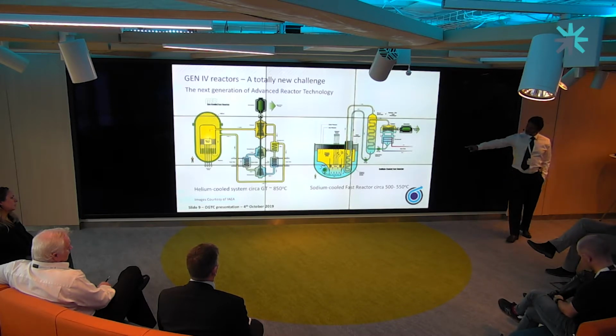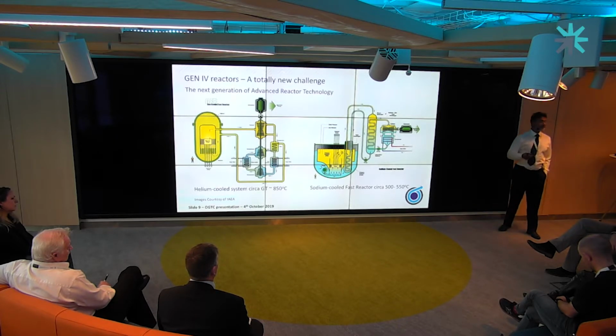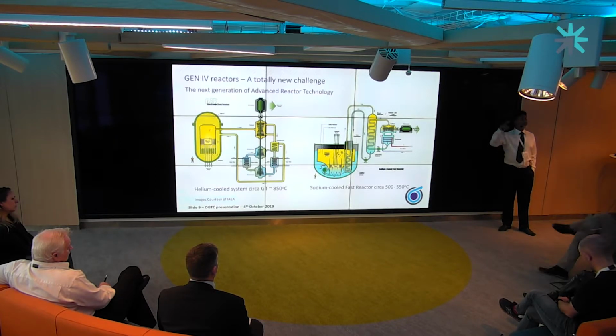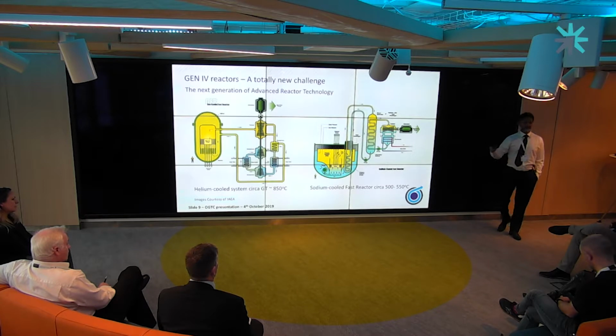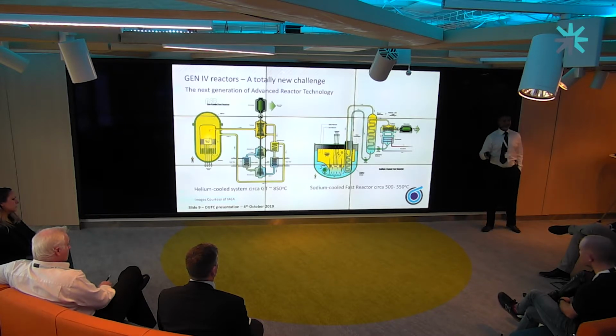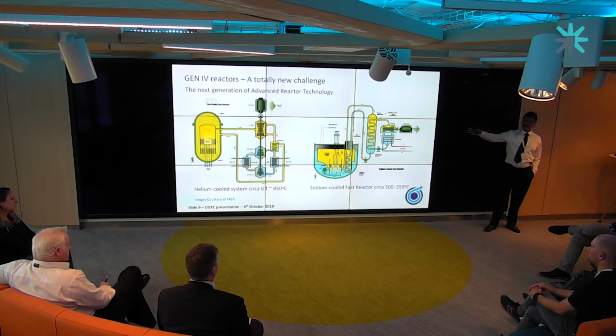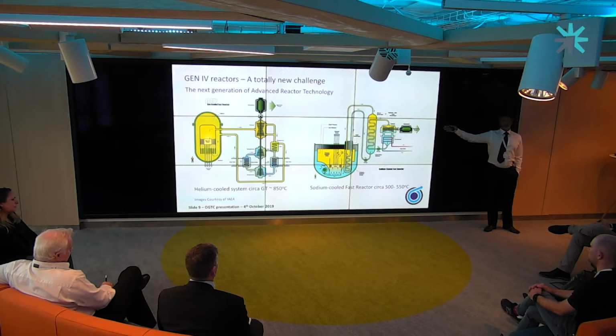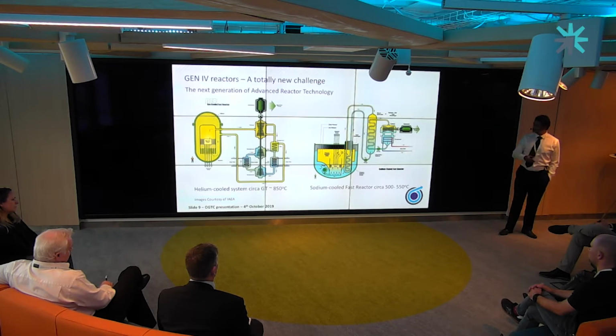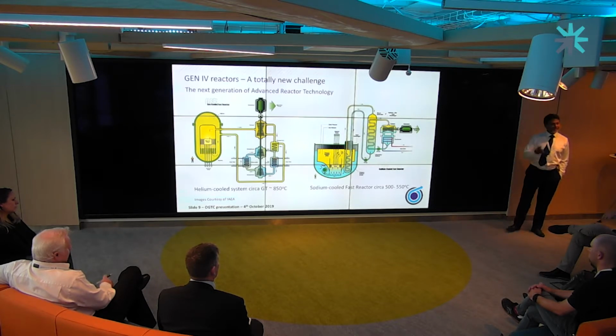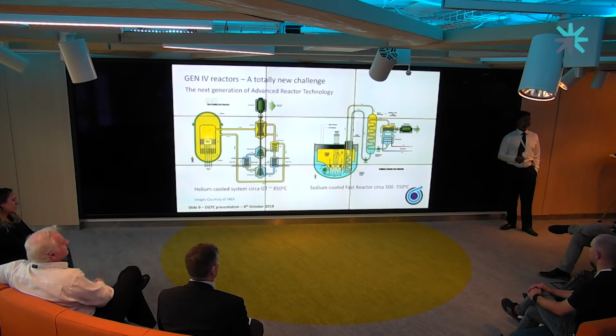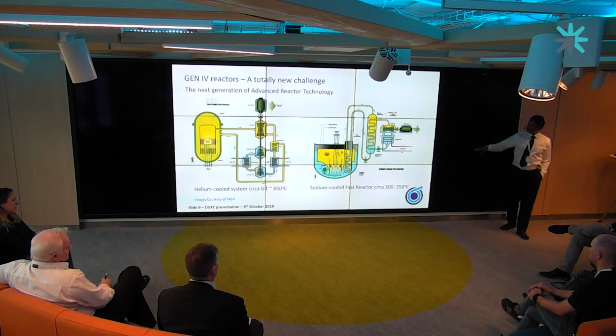So the goal here is if we used helium-cooled or we move to the likes of high-temperature gas cooling reactors, we can actually use hydrogen as a burn-off, as a reduction agent, instead of carbon dioxide and carbon monoxide for making steels. So there's an opportunity there to start benefiting what we call combined heat and power, but applied to nuclear, but also hydrogen generation to use it as another source, moving away from CO and CO2. On the right-hand side, sodium-cooled reactors or liquid metal reactors, they're another challenge. How does liquid metal flow around and actually start to cool the reactor? And metal interactions there are very much a different setup.